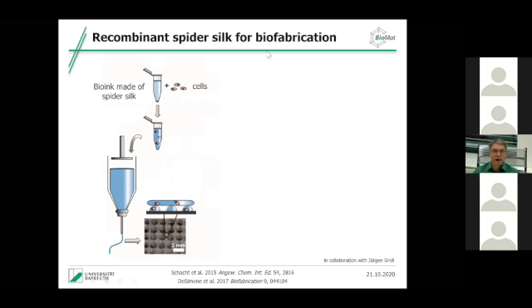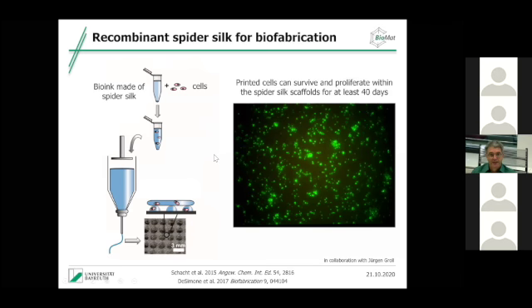And this is what is called biofabrication. So the simultaneous printing of the hydrogel with the cells. So we mix the cells with our spider silk ink, and then we print that together. And all of a sudden, the cells are in place. They don't have to migrate anymore. And the first thing we looked at was, do the cells survive that? Because if you just print cells without any scaffold, they're dead. Most of the cells die.